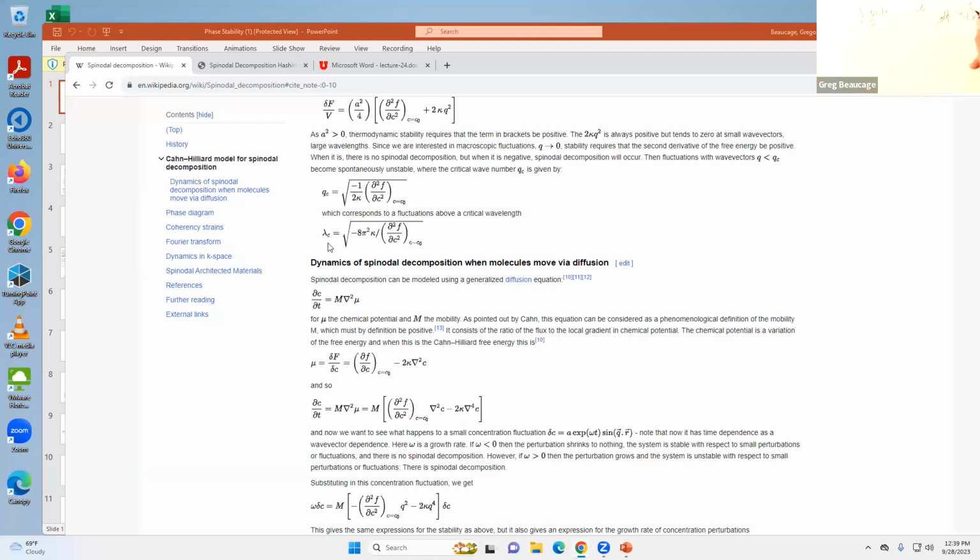That's the idea of nucleation and growth. In spinodal decomposition, it just spontaneously happens. So here you don't have this kind of gradient term, but here this adds to the free energy of the system. So you have some kind of gradient term that's going to be dependent on del of the concentrations. It's going to be like dc/dx, right? But since that ends up giving you a vector, you have to square it.